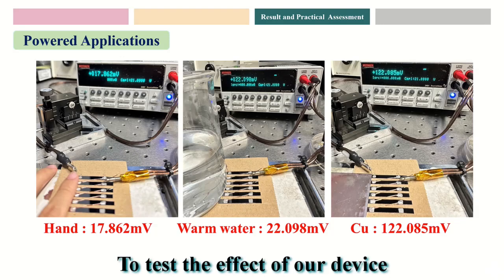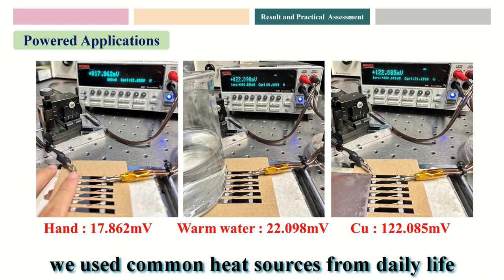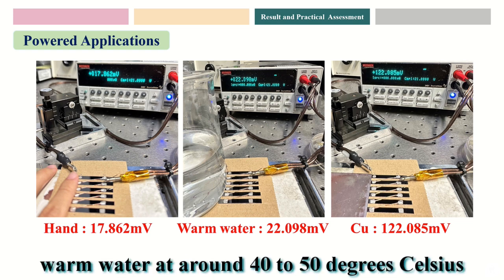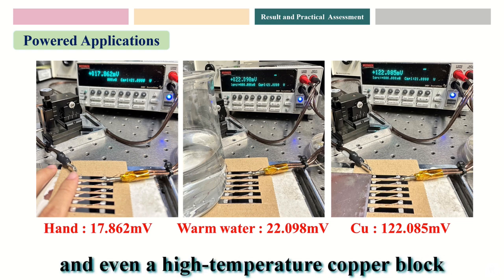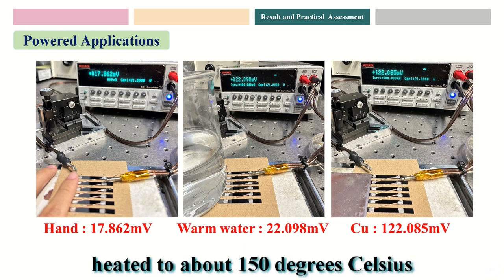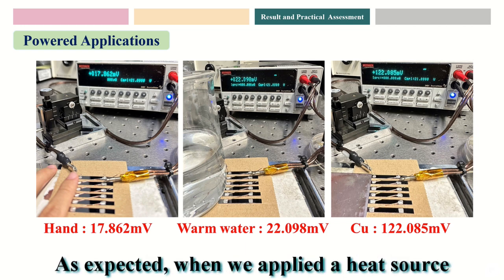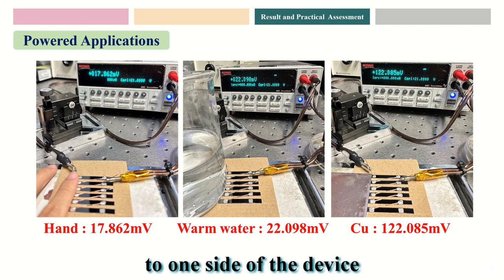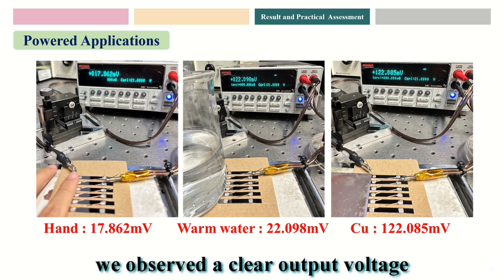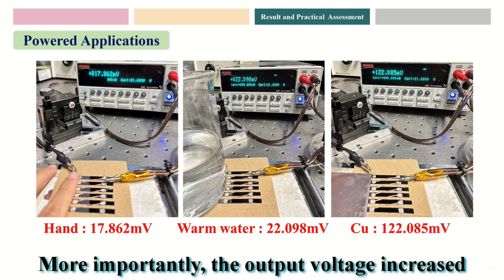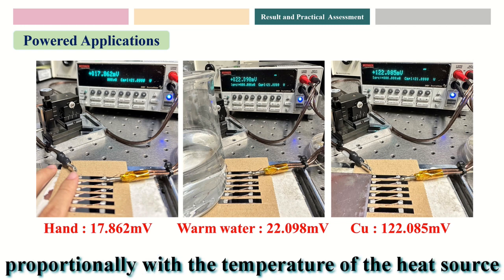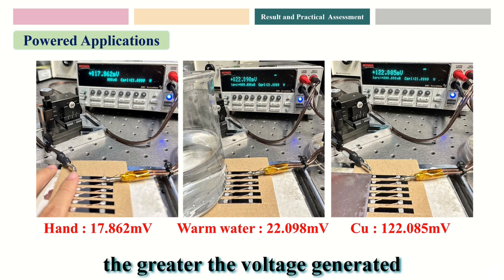To test the effect of our device, we used common heat sources from daily life, including the human fingertip, warm water at around 40 to 50 degrees Celsius, and even a higher temperature copper block heated to about 150 degrees Celsius. As expected, when we applied a heat source to one side of the device, we observed a clear output voltage. More importantly, the output voltage increased proportionally with the temperature of the heat source. The hotter the source, the greater the voltage generated.